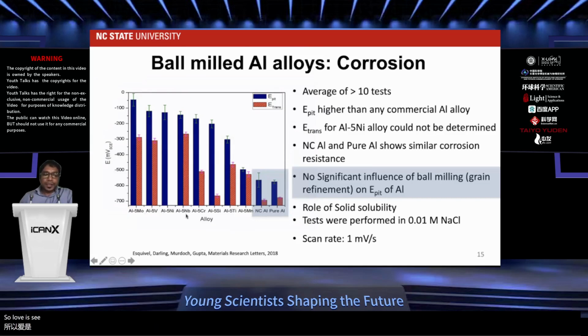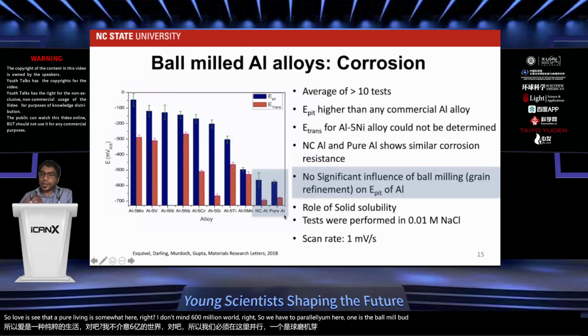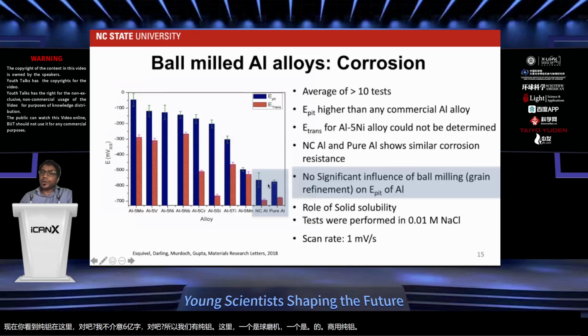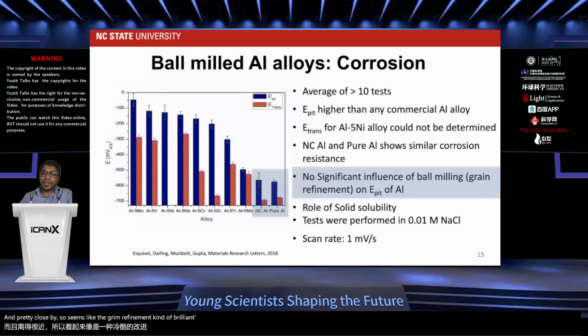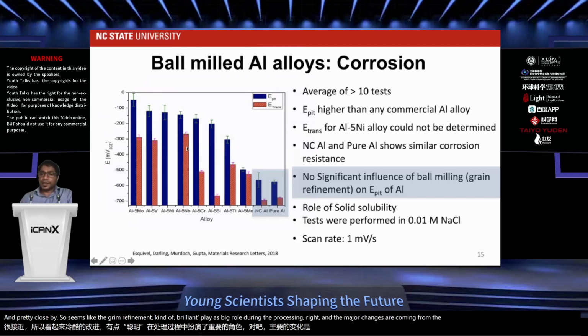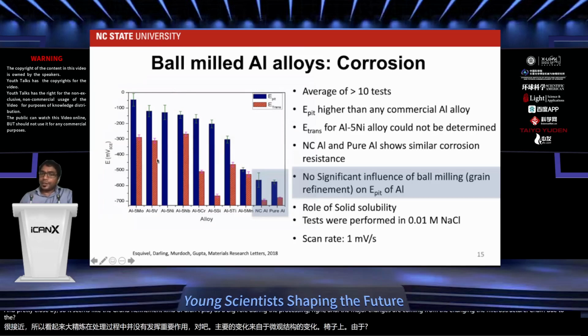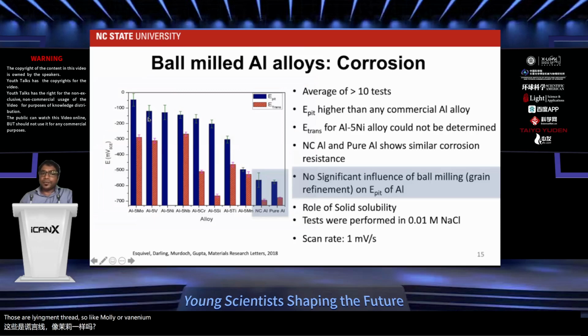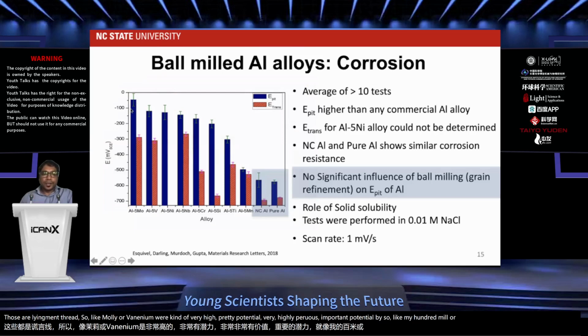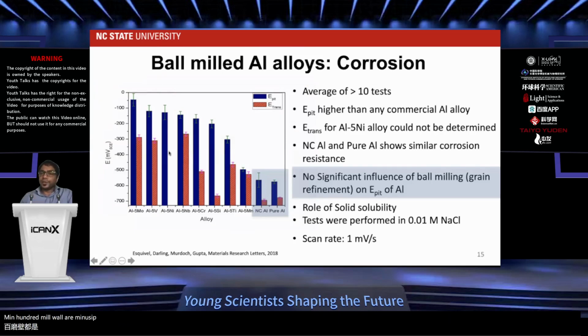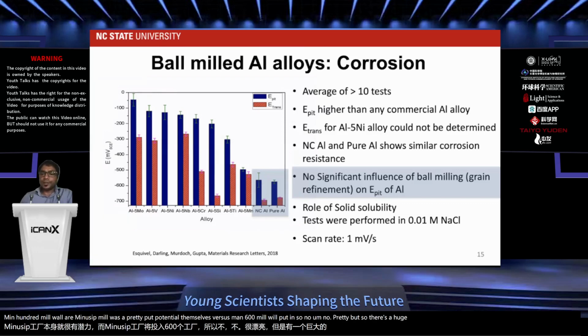So now you see that pure aluminum is somewhere here, right? Around minus 600 millivolts. We have 2 pure aluminum samples here. One is the ball milled, one is the commercially pure aluminum, and they're pretty close by. So it seems like the grain refinement didn't play as big a role during the processing, right? And the major changes are coming from the change in the microstructures due to those alloying elements, right? So molybdenum or vanadium have very high pitting potential, very high repassivation potential, right? So like minus 100 millivolts or minus 50 millivolts pitting potentials versus minus 600 millivolt pitting potential. There's a huge increase in the corrosion resistance.